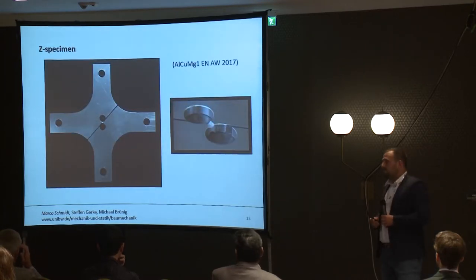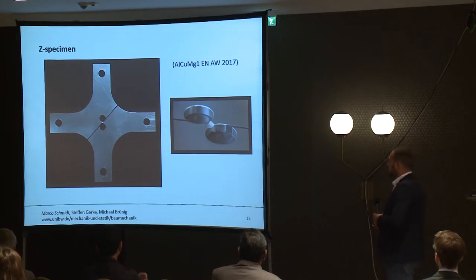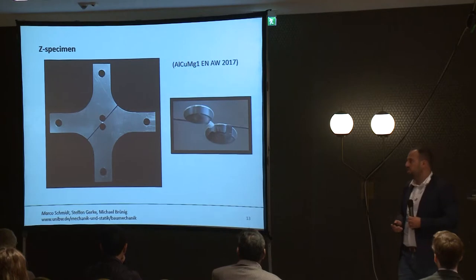That is the biaxial specimen, also called Z-specimen. It's made of an aluminum alloy and results from the idea of the one-dimensional shear specimen. And it's supplemented by two more arms. Now it's possible to superimpose the shear load with tensile or compression load.